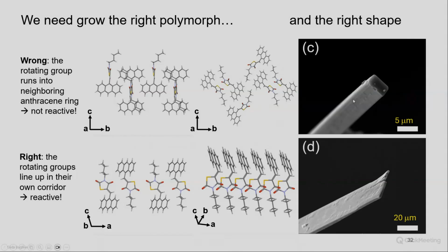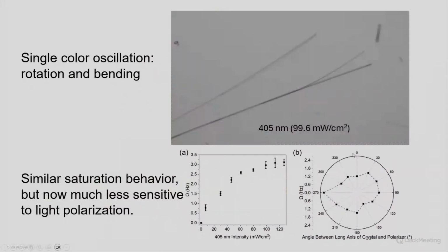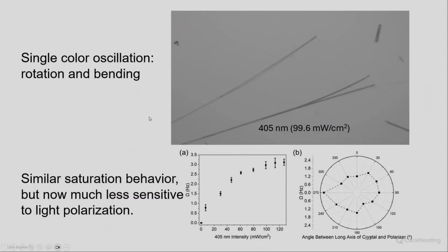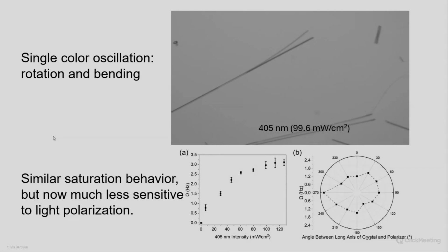And then again, these are single crystals. These are two examples of single crystals of polymorph B, the good polymorph, that shows we can grow them in well-faceted microwires. These are SEM images. And indeed, under a single wavelength illumination, these guys will just oscillate away. This is a twinned crystal, so it had two ends, so it's very easy to see its motion, but you can also see other crystals moving in and out of the frame. And again, this is single wavelength illumination from just a light from your microscope that makes these guys move around.